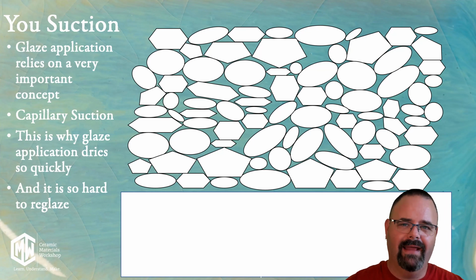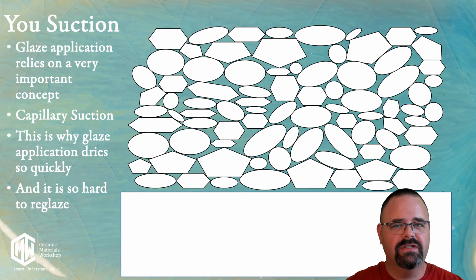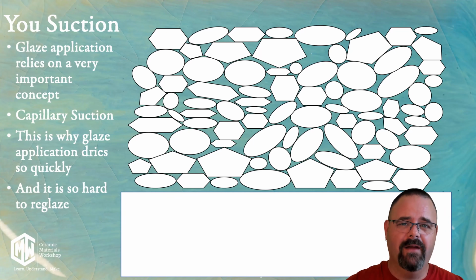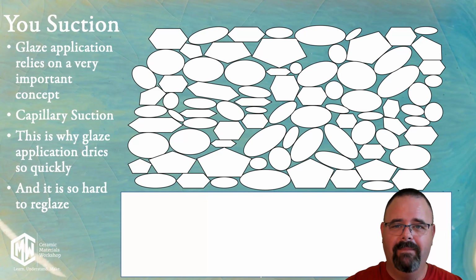This is why re-glazing a pot that's already been fired to temperature is so difficult because there is no capillary suction. We have melted the glass and glass doesn't have any suction, but open bisqueware does. When you're trying to reapply glaze to an already fired surface, you are hoping that the water evaporates, but it really doesn't, which is why it just tends to run off, and the solution for making a glaze stick to an already fired piece is to heat that piece up. The heated piece then becomes a radiator, which forces the water to evaporate, and then you can get some reapplication. But that is a dip application when you are going to dip in and rely on capillary suction.